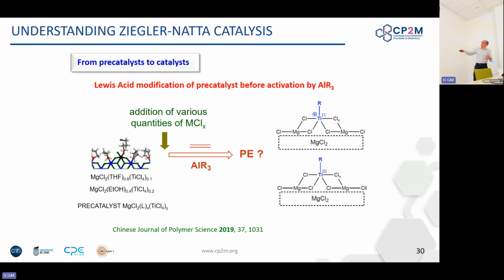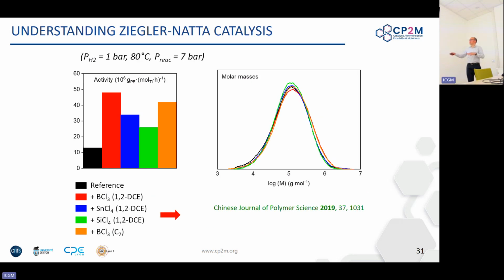I said that you need to tune the surface of magnesium dichloride with Lewis base. You can remove some of them with treatment with Lewis acid to increase the number of pre-active sites that we turn to useful polymerization sites. This is what we did with a variety of Lewis acids. So you can use boron-based Lewis acid, tin-based Lewis acid, silicon-based Lewis acid. You can vary the solvent, and you end up with just an increase in activity. You keep the exact same features for the polymer, okay? Exact same kinetic features, just an overall increase in activity, which means that you just increase the concentration in active sites. That's it.